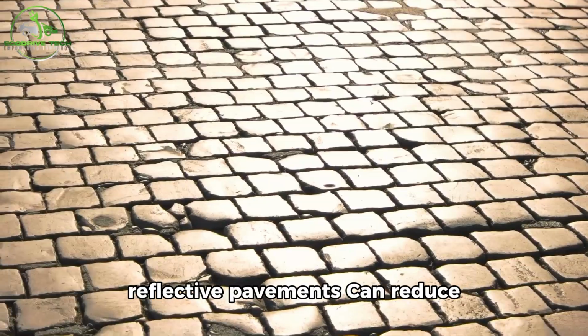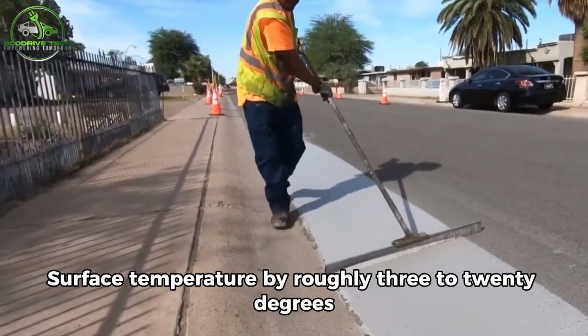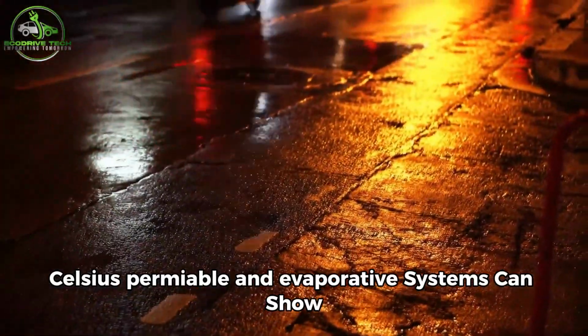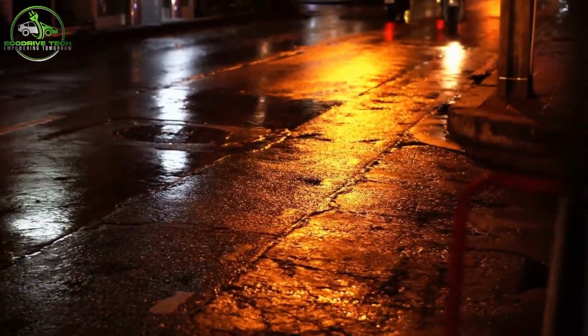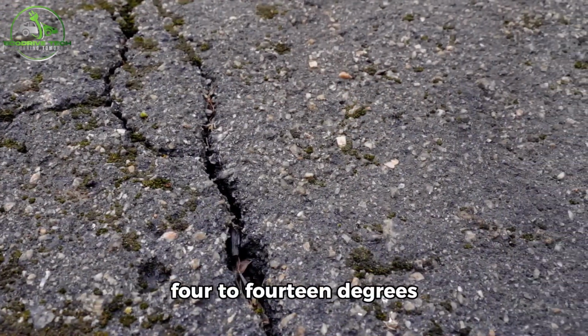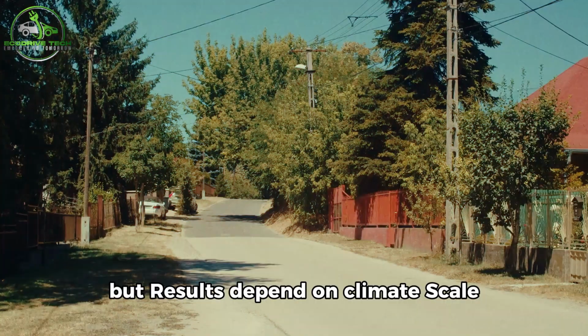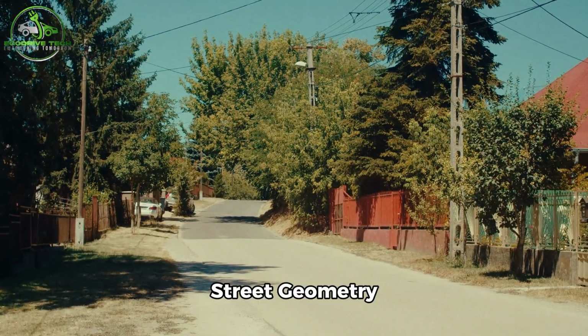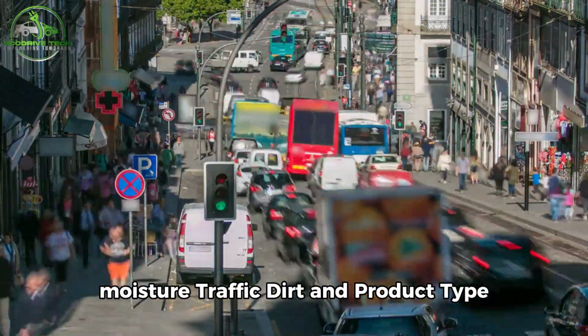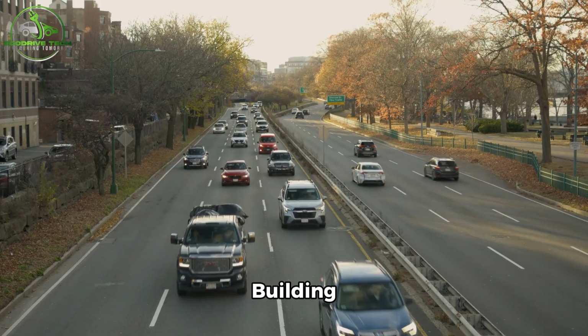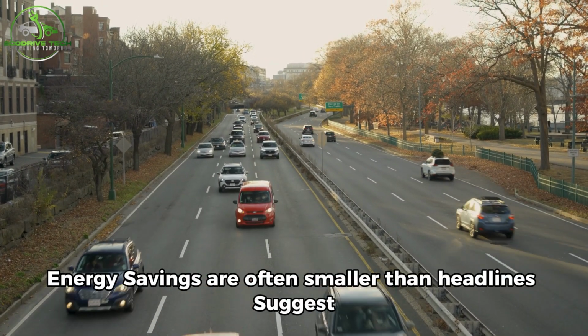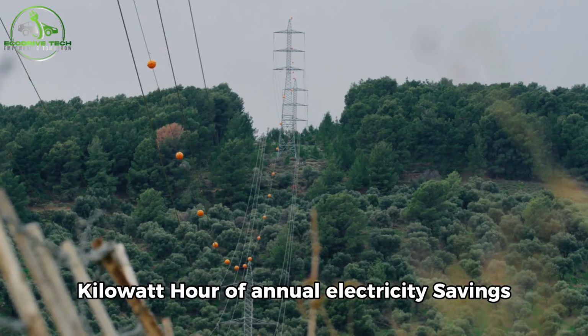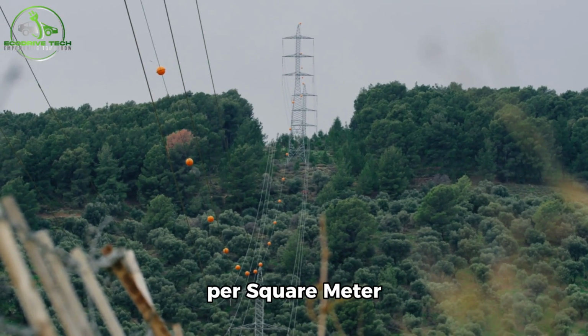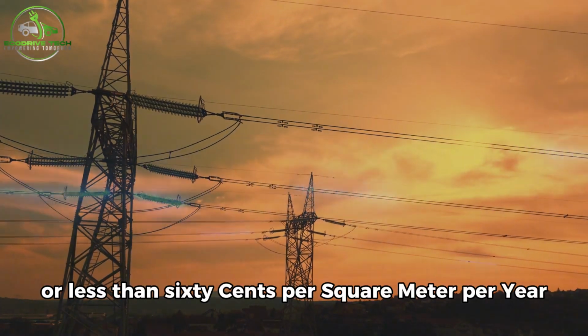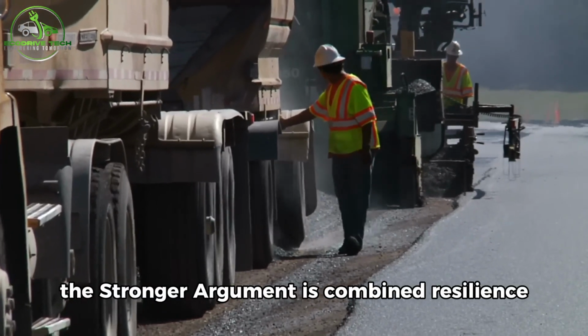Across the literature, reflective pavements can reduce surface temperature by roughly 3 to 20 degrees Celsius. Permeable and evaporative systems can show 8 to 25 degrees. Thermal storage systems can show 4 to 14 degrees. Large-scale applications have reported 4 to 19 degrees. But results depend on climate, scale, street geometry, moisture, traffic, dirt, and product type. Building energy savings are often smaller than headlines suggest. Some studies found less than 1 kilowatt-hour of annual electricity savings per square meter, or less than 60 cents per square meter per year. The stronger argument is combined resilience.